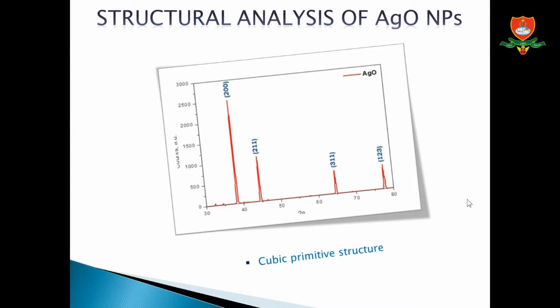Structural analysis of silver oxide nanoparticles. All diffraction peaks are attributed to crystalline silver oxide with a cubic primitive structure. The data obtained are in good agreement with the Joint Committee on Powder Diffraction Standards, JCPDS card, for silver oxide.